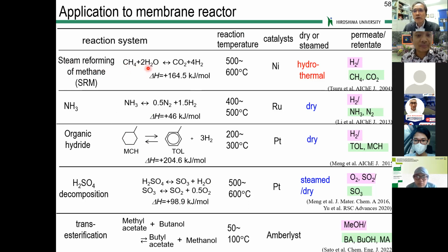The case of steam reforming: methane and water react to produce CO2 and hydrogen. Usually this conversion is limited by the equilibrium. To have higher conversion, this reaction should be operated at maybe 800 or 900 degrees, but by removing hydrogen, not the CO2, only hydrogen, you can shift this reaction to the product side. So you can also reduce the reaction temperature from 800 to 500 degrees. It is a dramatic energy saving or cost reduction for the chemical plant. So usually our membrane only removes or extracts hydrogen from the system.